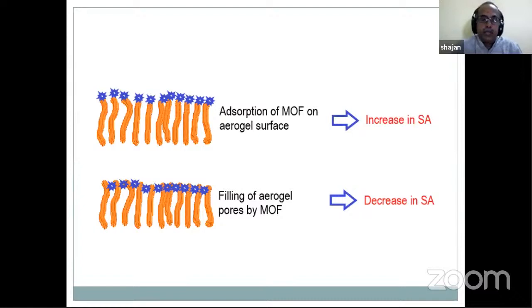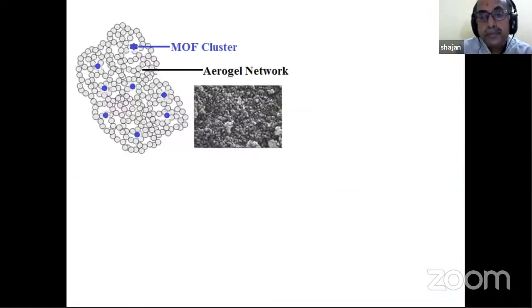In our experiments, we observed that when we use cobalt, the surface area is increasing. It is going beyond 300. So the reason is very clear. Nickel BTC has a very low ionic radius, whereas compared to it the cobalt ionic radius is large. So it cannot go inside the pore, it is sitting on the surface.